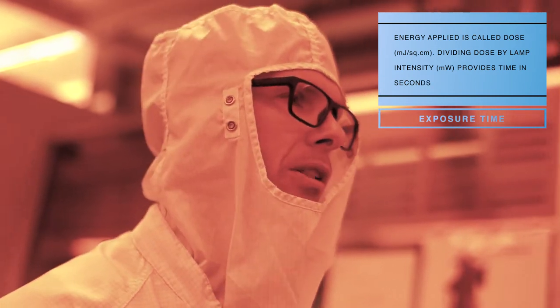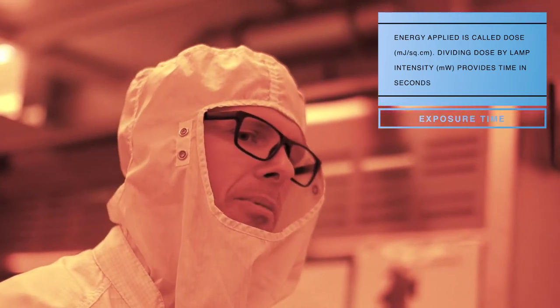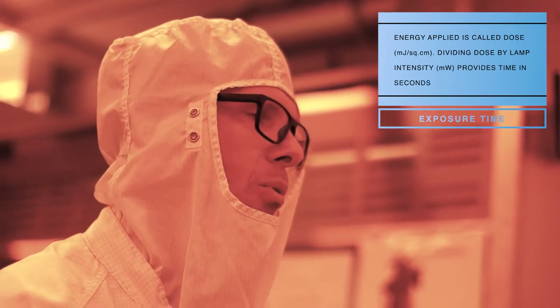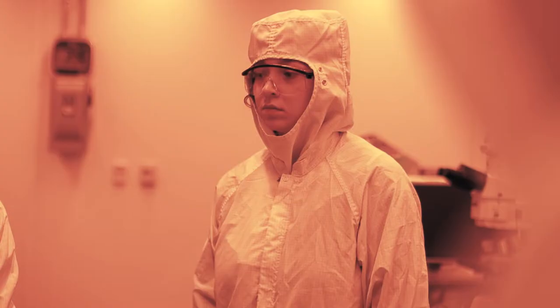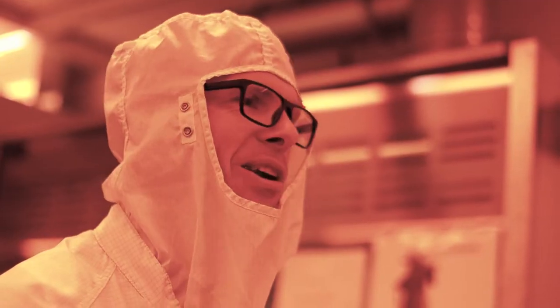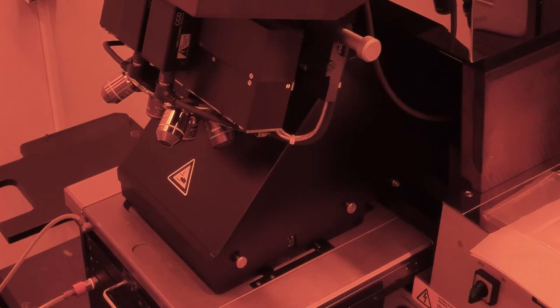So this says 150 millijoules. My lamp is about 20 milliwatts. I calibrated it, so about 7.5 seconds. So let's just do that. I think that'll work. All right. Now it's going to do its thing.